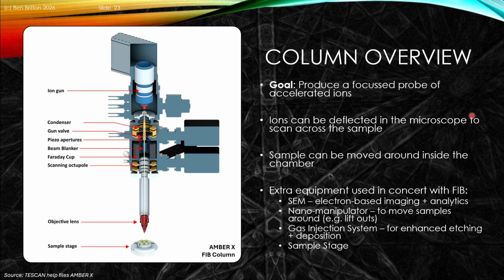Now, the sample itself is typically mounted on the surface of a carousel and stage, and so we might have, for instance, X, Y, Z, and R that enables us to move the sample around the chamber. So we can exchange from looking perhaps at our sample to also we could then move over and shift over to a handling grid that will enable us to pick up our nano or micron sized sample and put that in a secondary instrument.